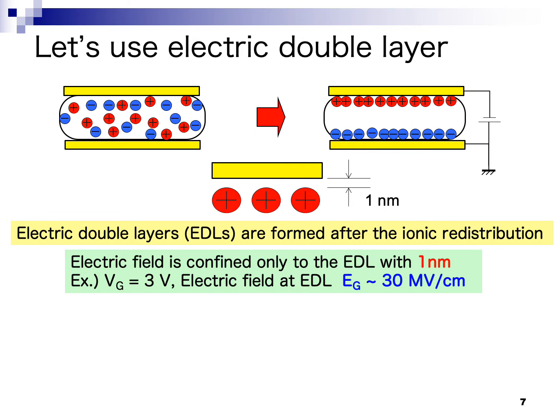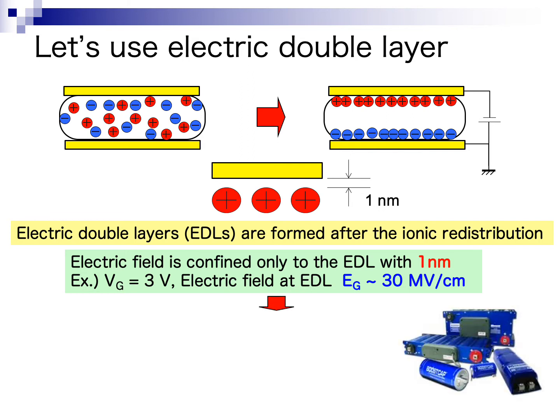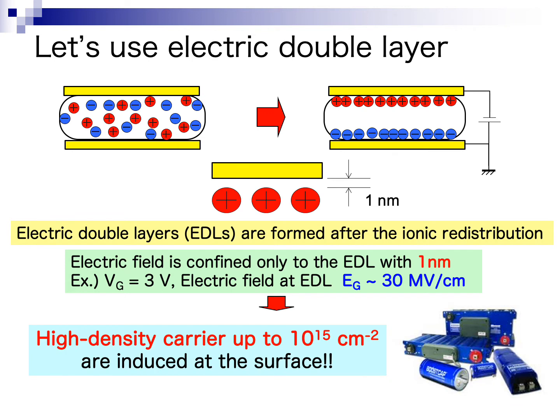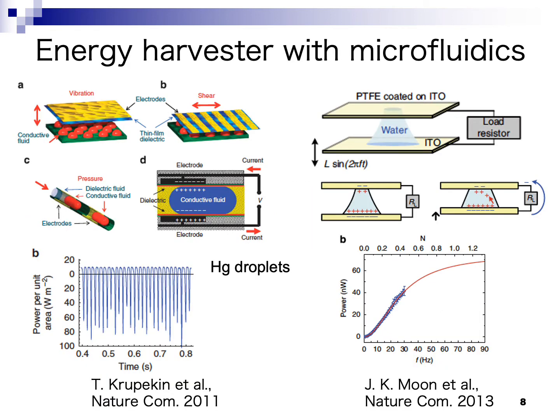Using this extremely high electric field, a high-density carrier of up to 10 to the power of 15 per square centimeter is induced at the surface of the electrode. There are several studies using an electric double layer in energy harvesters. But one work uses a mercury droplet. Another work uses water as an electrolyte, but since it doesn't use ions, the capacitance of the electric double layer is not so high.